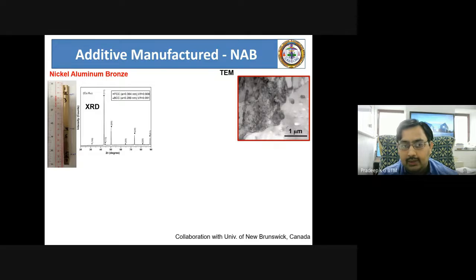Now, if you take this material in an electron transparent fashion to a transmission electron microscope, you can see here a defect, which is a grain boundary, separating the 2 grains, and you have these tiny precipitates of nanometer scale across the entire volume. But to image something like this, we have to go to a large enough field of view and see a limited volume, but we still don't know about the orientation of these precipitates and their crystallographic nature. Even if you do a diffraction, we can do it for only one of the precipitates. If you want statistical information on these additive manufactured materials, which is crucial, then we cannot rely on a transmission electron microscope to get this information.